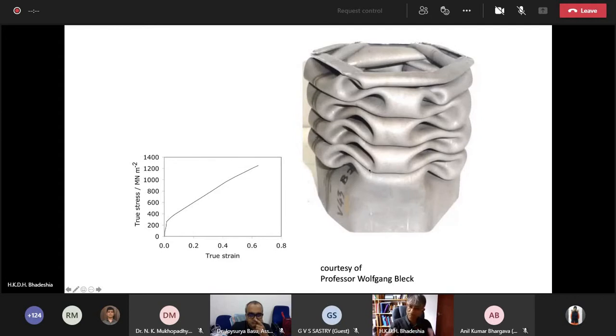Whereas, if you had a material which started off quite strong and had a stress strain curve like this, then it would absorb much more energy. So it turns out that it's not actually suitable for this crash resistant application, simply because it starts off quite weak and then reaches a strength of 1.2 gigapascals. And the way in which this component is designed means that you do not get uniform deformation. So much of this remains at a low strain.